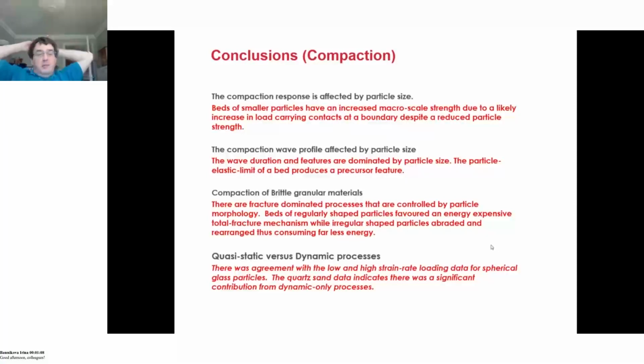So there is an agreement between low and high strain rate loading for spherical glass particles. But when you get onto irregularly shaped sand with all its flaws and particle sizes, no, there's dynamic-only processes that appear to be occurring. So what we have is a fairly complex situation where particle size, flaw density, particle shape, and packing all are quite significant. And then if you want to add some water in there, you will get some extra response as well. So that is why granular materials are quite extensively studied and also quite difficult to come up with a consistent theory for polydispersed granular particles. If you can keep the granular particles about the same size, life is generally more straightforward.